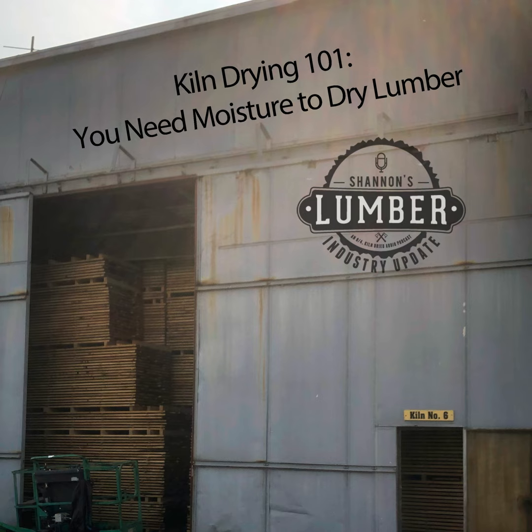So we're doing that manual sampling mostly to check for tension, but we're also doing a double check on the moisture. If the moisture probes say 12%, well, this part of the kiln is reading 14%, this part of the kiln is reading 10%, because you're going to have some variance in a large kiln. It's the advantage of using a smaller kiln, you won't have as much variation. There's a lot of other variances there, but I often tell people to look at kiln schedules because they're public domain.